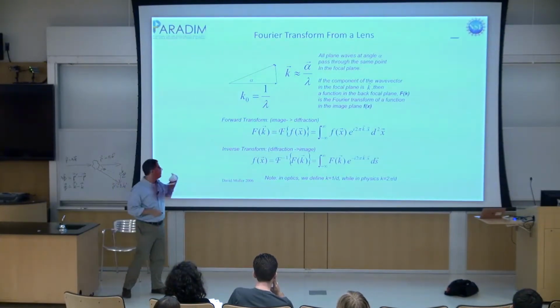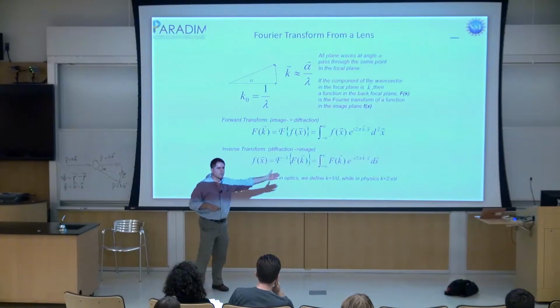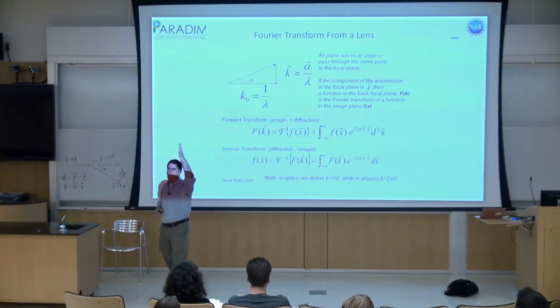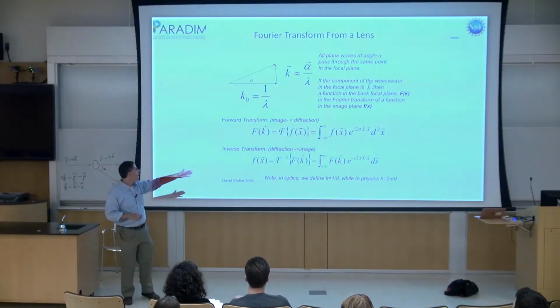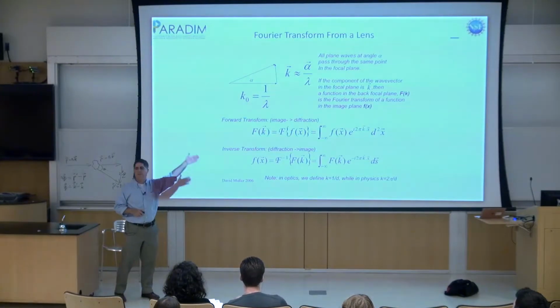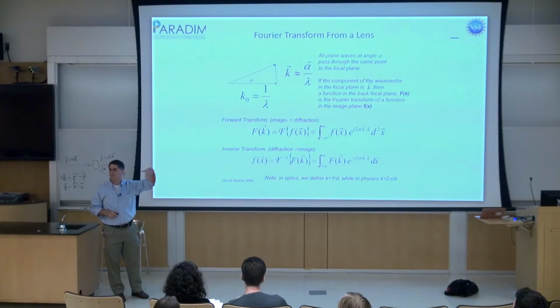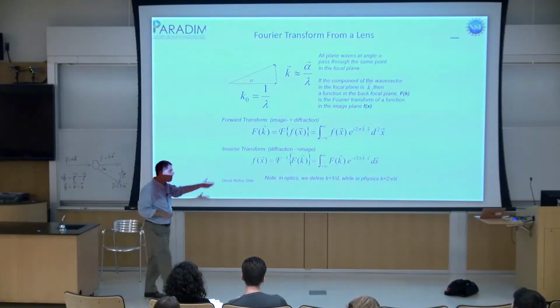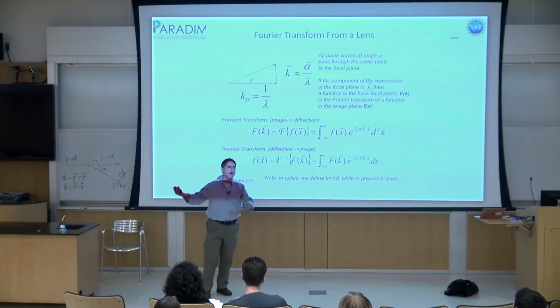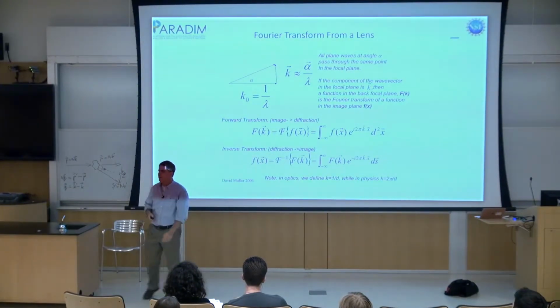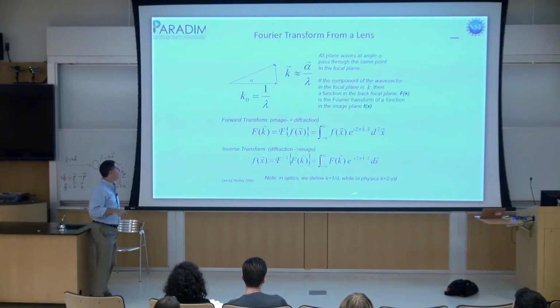So when you look at crystallography inverse angstroms, you just read it off as 1 over angstroms, and if it says 0.5 inverse angstroms, that means a 2 angstrom lattice spacing. If it was the physics notation and it said 0.5, I'd go, well, that's 2 times 2 pi is 12, and I've got to remember to divide or multiply, and you get in a mess. So crystallographers are very practical, but they don't expect to do algebra.